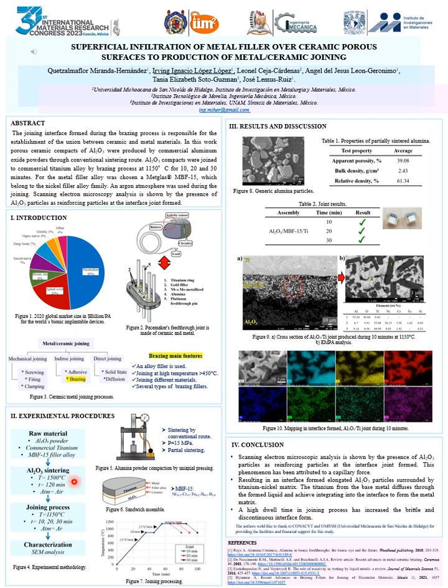To make the joints by brazing, the following steps were taken. First, the surfaces of the titanium and aluminum oxide compacts were roughened by silicon carbide sandpaper. The materials were cleaned for 5 minutes in an ultrasonic bath with ethyl alcohol. Finally, the pieces were assembled in a sandwich-type arrangement: aluminum oxide plus filler metal plus titanium. The assembly was carried out inside a graphite die. The joints were carried out at 1150 degrees Celsius for dwelling times of 10, 20 and 30 minutes in an Ar atmosphere. Transverse sections of the joined samples were prepared to obtain mirror-like surfaces in order to be analyzed in a scanning electron microscope.